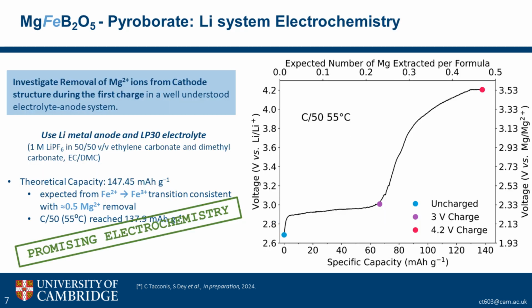So now focusing more on the key part of my work, we made the material, and what we wanted to do was to look at whether we were able to remove the magnesium from the cathode structure. So what we decided to do was to cycle the cathode and look at just the first charge in a well-understood electrolyte anode system that could go through the voltage range that we were hoping to charge it at. And so we decided to use lithium metal and LP30 electrolyte, which are some standard lithium electrolyte anode systems that are used.